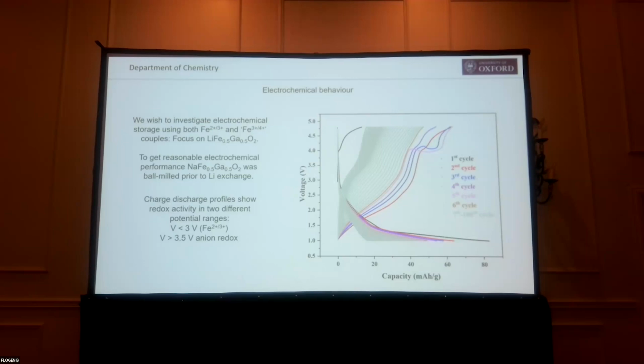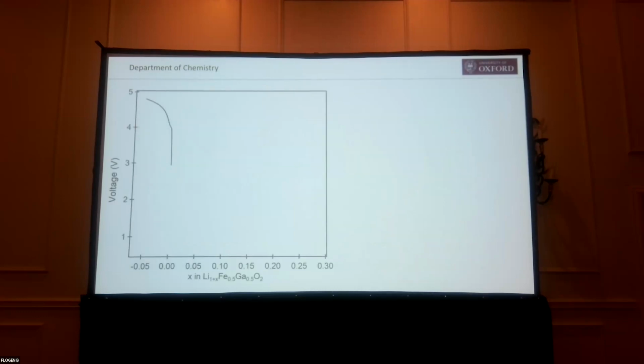And if you look at the data, you can see it looks a bit strange because it looks like we've got two types of features. You can see there are some features like here in the oxidation, which are really high, and then in the oxidation down here, you see there's a low percentage. It's like we've got two separate processes. As if we've got this iron 2, 3 redox couple, and then something else that happens, which we would think is the oxygen. So we can plot this data in a slightly different way. What we can do is plot out the same data, but now we'll run in total of how much lithium we've got on the plate.